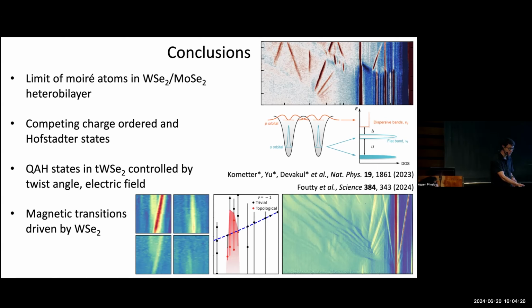To put numbers on it, for a twist angle of 1.5 degrees, the Moiré wavelength itself is probably about 10 nanometers. The super Moiré wavelength can be several hundred nanometers, so it grows very rapidly. At some point, you may not care about that super Moiré wavelength, and that also is, I would say, still an open question. There are examples where that super Moiré wavelength does do important things, but I'm not sure it always necessarily has.